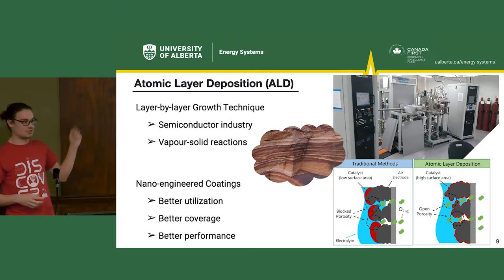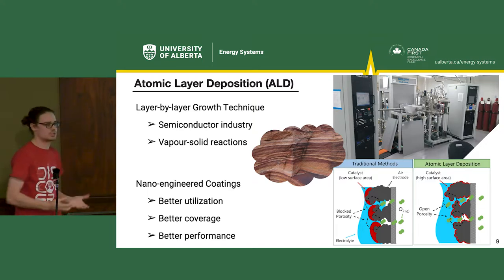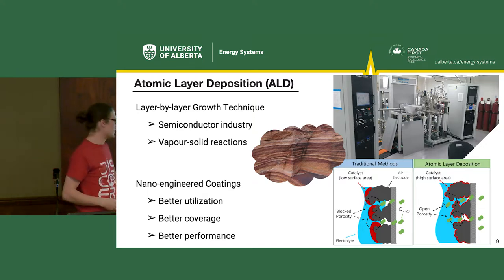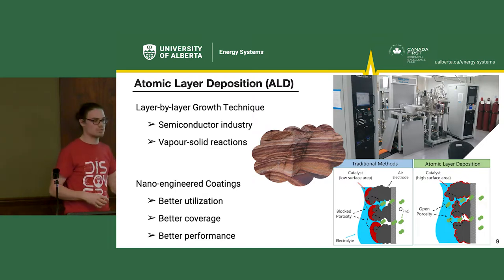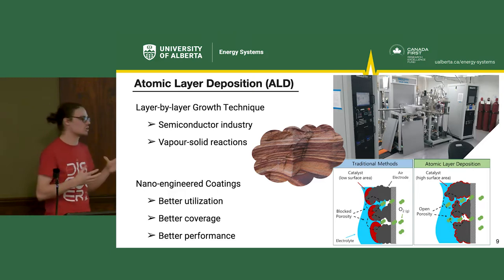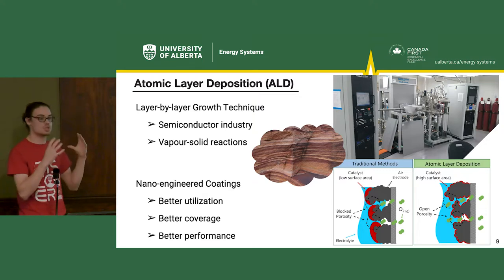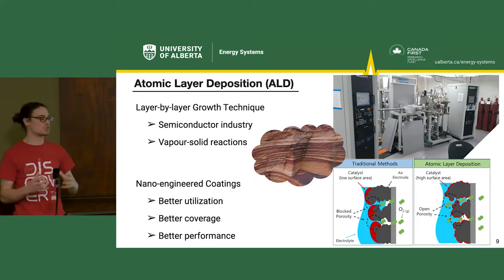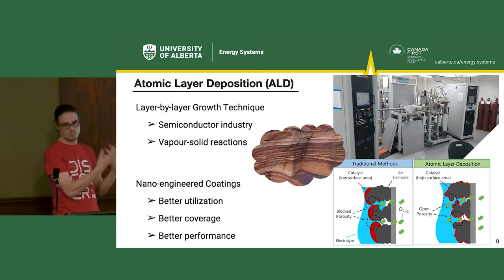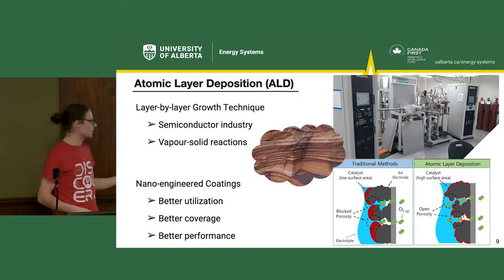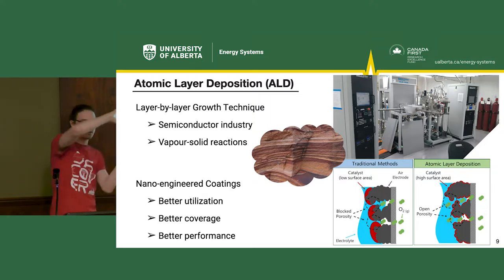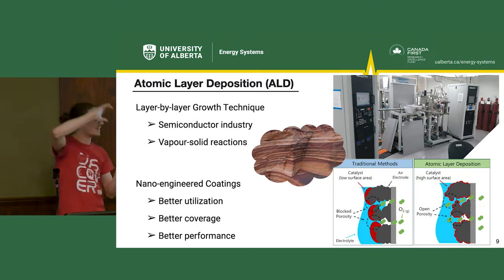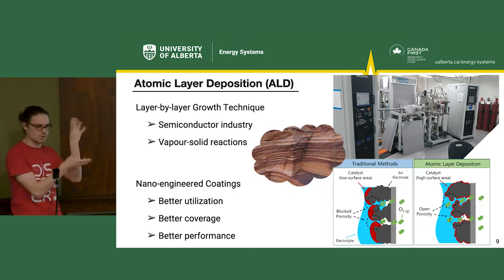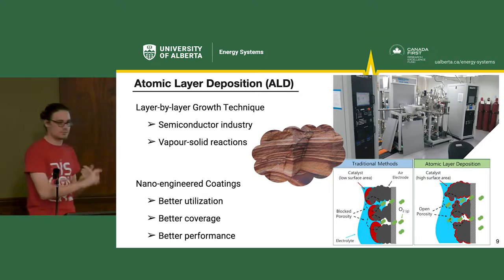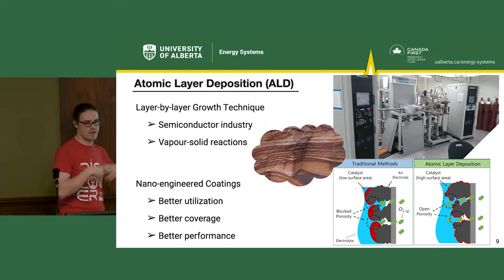Now, with this technology, this ALD, I can make iron oxide catalysts that are better than just throwing iron oxide rust on my battery, because if we just threw chunks of it, we might block pores in that air electrode. We need oxygen in and out of the battery. If we block those pores, it's not going to work anymore. And also, I can enhance my surface area. Now, catalyst surface area is everything because the catalyst actually works on the surface. So the more surface area, the more reactions you're going to have catalyzed. So with my ALD, you can see on the right there, that schematic, I get a thin conformal coating of iron oxide, my rust catalyst, all through the particles of my air electrode. That's kind of what the air electrode looks like. So that enhances the performance, enhances the utilization, so we don't waste material.